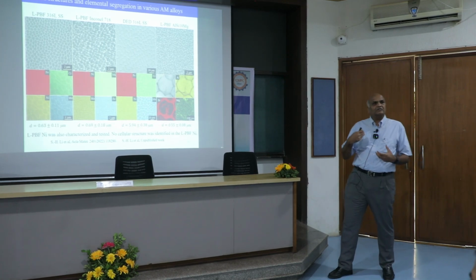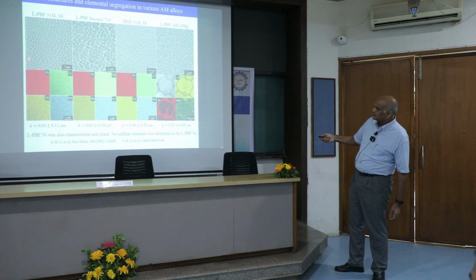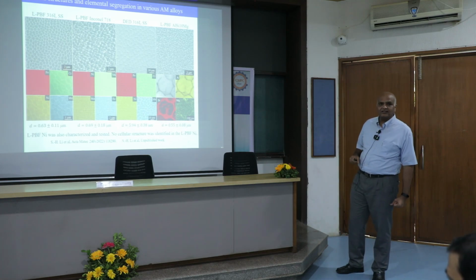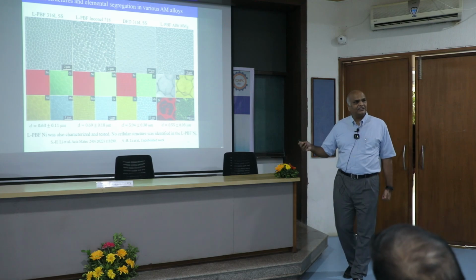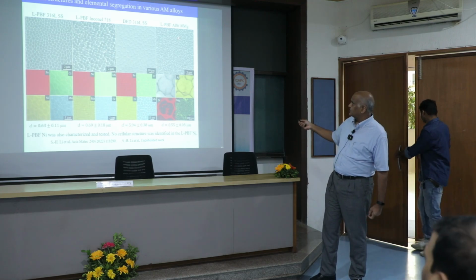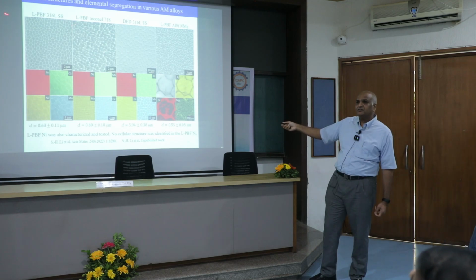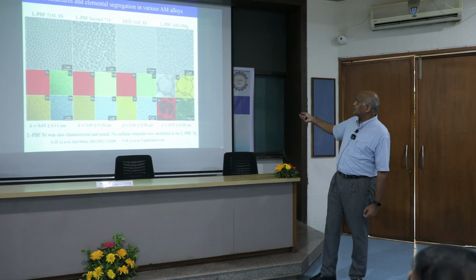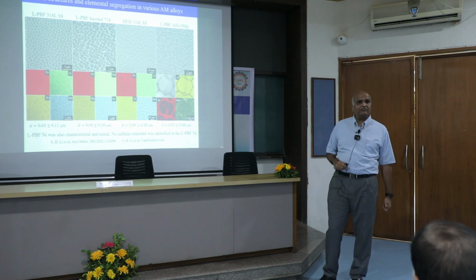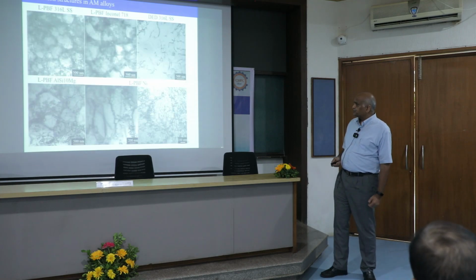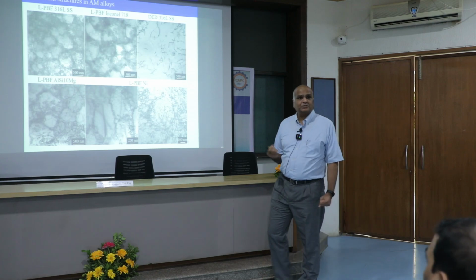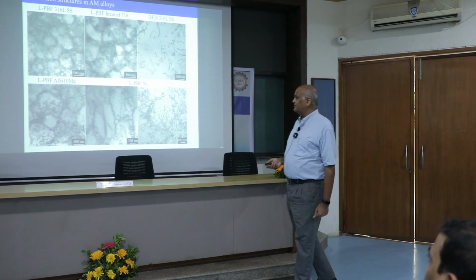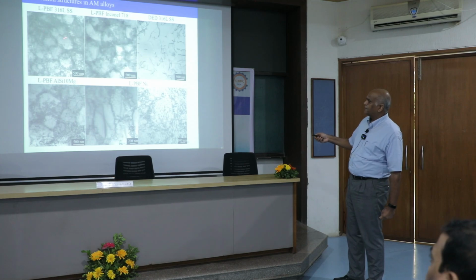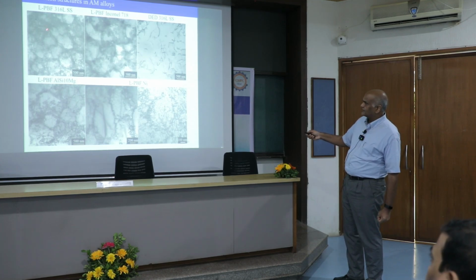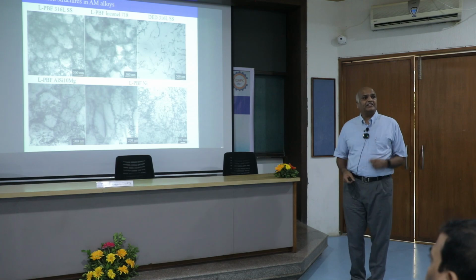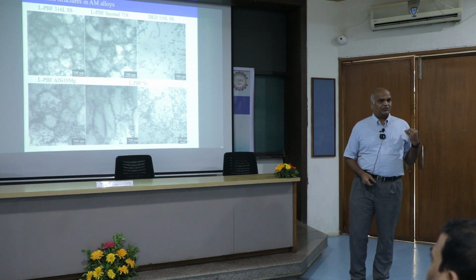These color maps tell you chemical composition, right? What you will notice is that chromium, molybdenum, nickel, these alloying elements, segregate to the cell boundaries. This is a super alloy, Inconel 718, which is a high temperature super alloy. This is the aluminum magnesium that we saw. All of them have these features. Then you do TEM, transmission electron microscopy, and you find additional features. It's basically these cell walls. This is a cell. You see, they are all decorated with lots of dislocations.